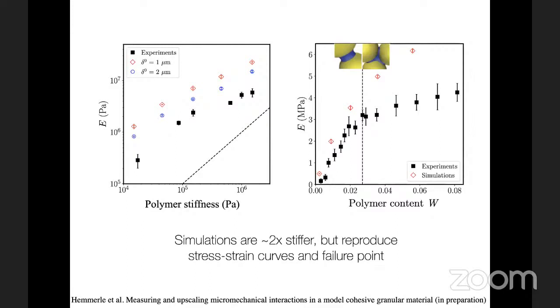If we put this in, we have spring constants that are derived from a gap of 1 or 2 microns. Those give slightly different possible choices of the spring constants in the numerical model. And we can compare the results to the measured Young's moduli for both changing the polymer stiffness and changing the polymer content. And the typical results are, as I said, about twice as stiff, but they show the same scaling, including some of the nonlinear scaling, up to the point where the polymer content undergoes this pendular to funicular transition, where, as I said earlier, we believe the physics to change.